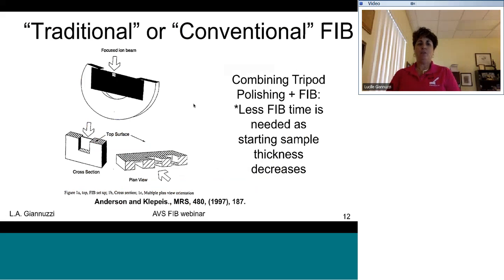Okay, so again, using the H-bar technique, but mechanically polishing the sample to the smallest dimension possible prior to FIB milling to just save FIB milling time. So this is combining a tripod polisher plus the FIB. Less FIB time is needed, so that the starting thickness is just thinner.